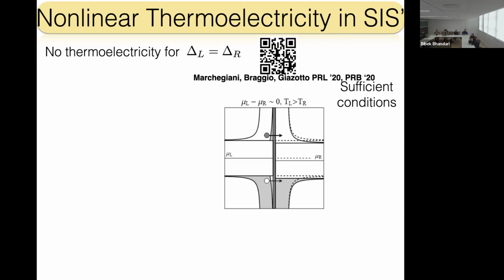Essentially, you have a superconductor insulator superconductor system, so SIS. And let's start by assuming that you consider the case of identical gap. If you assume identical gap, you have this type of scheme where, please note that I assume to put temperature finite here and zero temperature here. I want to be extreme, okay? If you do that, you realize that here you have some quasi-particle state, quasi-hole state. But now what happens is the following, that you realize immediately that the only response that you can get from this system in the presence of a gradient of temperature is dissipative.